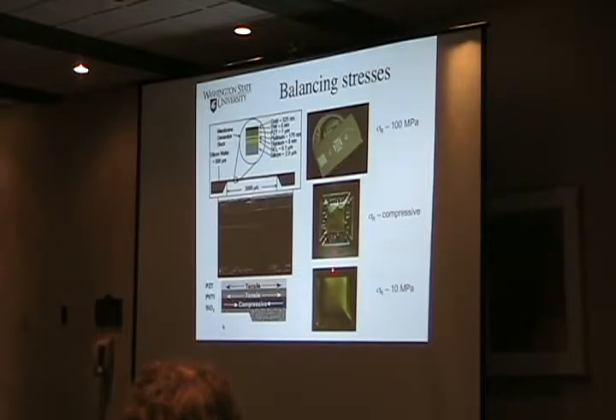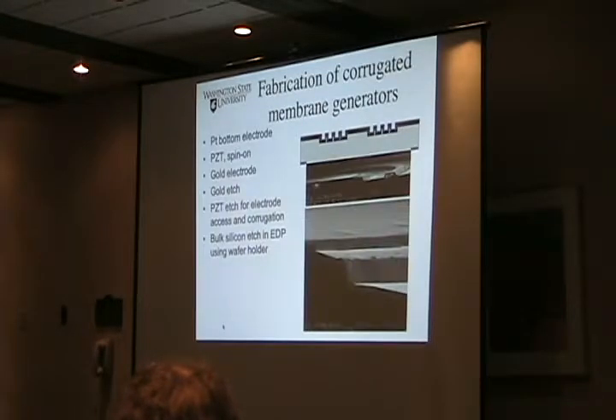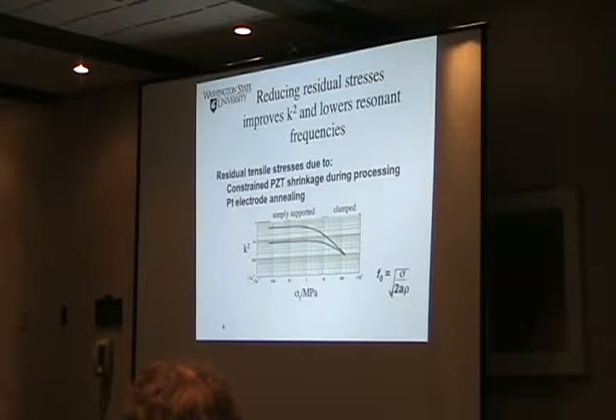So we then backed up and said, well, let's stay just barely slightly tensile. And we did that by sticking in this compressive oxide. There's our titanium-platinum electrode, which is tensile, and the PZT, which is the biggest tensile component. So the overall membrane, or diaphragm, now has a stress of about 10 MPa instead of what we started with at about 100 MPa, which should give us something like an order of magnitude increase in our k-squared.